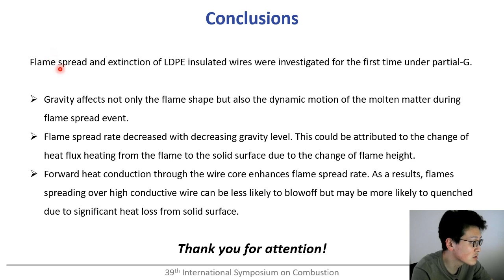So in conclusion, flame spread and extinction of LDPE insulated wires were investigated for the first time under a partial gravity environment. Gravity affects not only the flame shape, but also the dynamic motion of the molten matter during the flame spread event, and flame spread rate decreased with decreasing gravity level. This could be attributed to the change of heat flux heating from the flame to the solid surface due to the change of flame height. And forward heat conduction through the wire core enhances the flame spread rate. As a result, flames spreading over a highly conductive wire could be less likely to blow off, but may be more likely to quench due to significant heat loss from the solid surface.